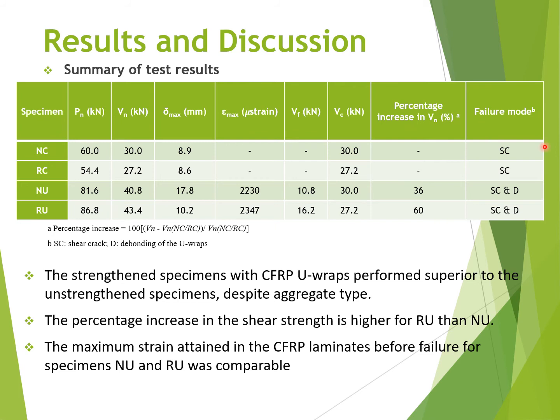It should be noted that due to the absence of steel stirrups in the beams, the shear capacity of NC and RC beams were considered the concrete contribution to shear capacity for the U-wrapped specimens, and consequently the FRP contribution to shear capacity was calculated by subtracting V sub C from Vn.